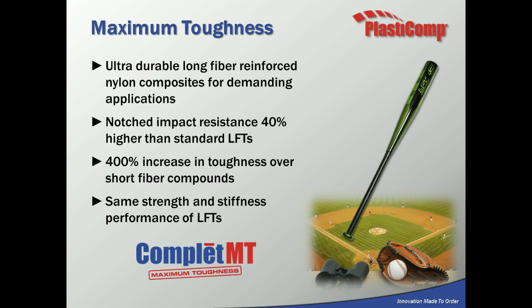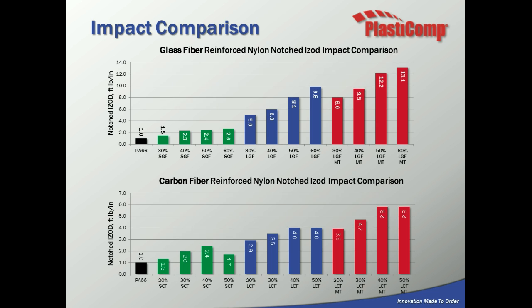Another grade is one of our maximum toughness grades, and this is a grade that we position in applications where they need high impact. A couple of points on this: we get about a 40% increase in notched Izod impact over standard long fiber thermoplastic materials, and we actually get about a 400% increase in toughness versus short fiber compounds. We get all this while maintaining the same stiffness and strength of the long fiber materials.